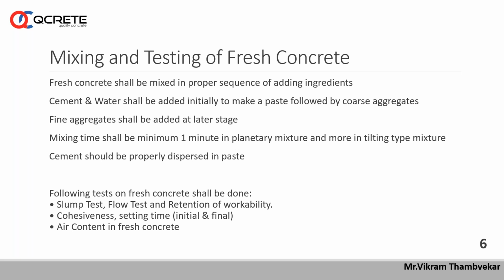And while making fresh concrete, the sequence of putting material in a mixer, either in an RMC plant or in a batching plant, or some of these regular mixers at site, should be followed properly so that all the paste and fine and coarse aggregate will get mixed to get a very good quality of fresh concrete. And to get flowability and workability, the admixture we are using should be used in a proper way. Before using chemical admixture, it should be stirred well so that all the solid contents of the chemical admixture are mixed with the concrete or with the water. If you are using water and chemical admixture together, it gives better effect.